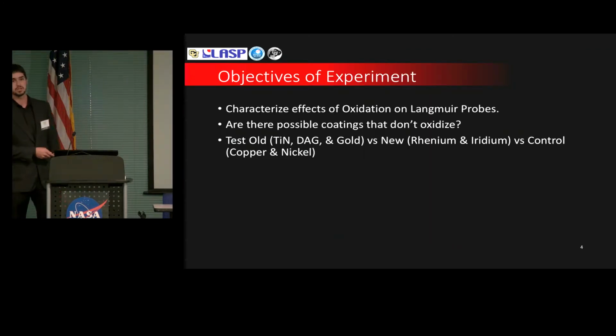So the objective of the experiment was to characterize the effect of oxidation on Langmuir probes. If you made a measurement with a deteriorated probe, what could you expect from the measurements gotten? Then to see whether or not there were possible metals or materials that wouldn't oxidize in these plasma environments, and then to characterize them correspondingly. So we tested titanium nitride, gold, and DAG. These are commonly used coatings, against test materials like copper and nickel, metals that are well known to be easily oxidized.